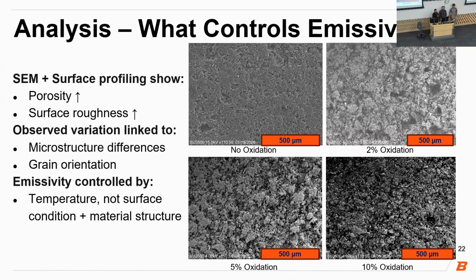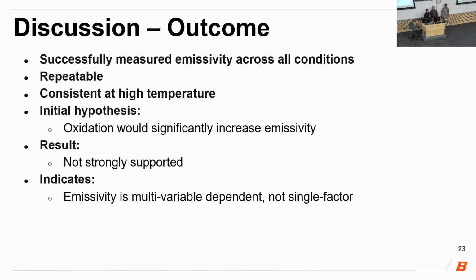And from these SEM images we took, we can see the differences in porosity and surface roughness between samples. This is an effect of oxidation. These types of features directly affect how radiation interacts with the surface, which can influence emissivity. So some of the variation in emissivity behavior is likely tied to the effects from surface structure and microstructural characteristics tied to oxidation. However, we were unable to make a clear connection between the structure and measured emissivity.